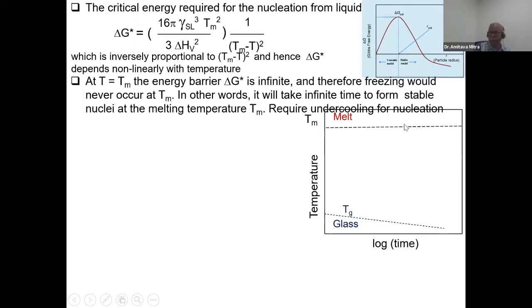So you require an infinite time to get it crystallized. If this is my melt temperature Tm, and this is the time, we are plotting a curve of temperature versus time, and this will be the transformation. At T equal to Tm, delta G is infinity. That means at the melting point, although we showed earlier that delta G sharply falls, it is not the case, because at delta T equal to zero, this is infinite.